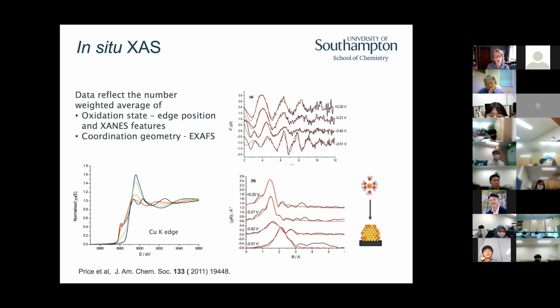It never gets all the way to the metal foil because the copper atoms don't have their full 3-dimensional structure of all the coordination that they would have if they were part of copper foil. You can see that the edge energy is shifting. As we change the oxidation state, it goes from copper 2+ to basically copper 0, or almost copper 0. We're watching the edge change, and we're watching this white line decreasing as well. So we're looking at the effects of the change in the coordination as well as the change in the oxidation state. You can gain a lot of information just by looking at the XANES region.